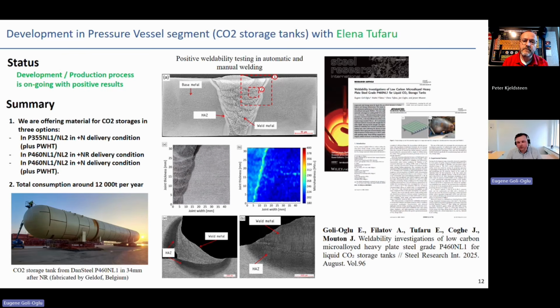And of course, this is for P460. For lower strength grades, for P355, it will normally be 210, 220 Vickers. Yeah. So the tests being made, all these spots you showed, notch test at minus 50 degrees C. Depending on the application, it will be made either at minus 20, minus 40, or minus 50 degrees. Yeah.